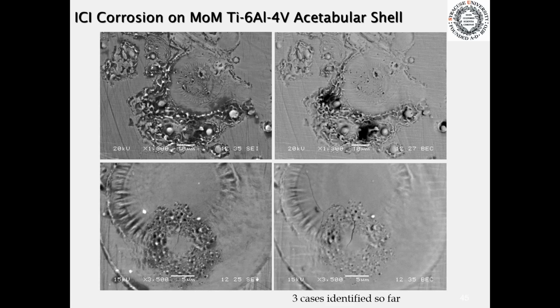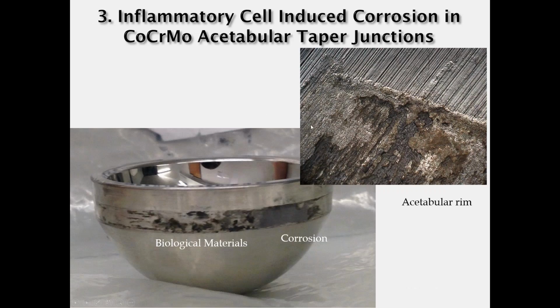More recently, we've seen actually evidence of attack on titanium 6-aluminum-4 vanadium as well, where very similar biological features appear as corrosion damage of a titanium 6-4 alloy acetabular shell. And indeed, we see some evidence of ingress of these inflammatory cells into taper junctions.